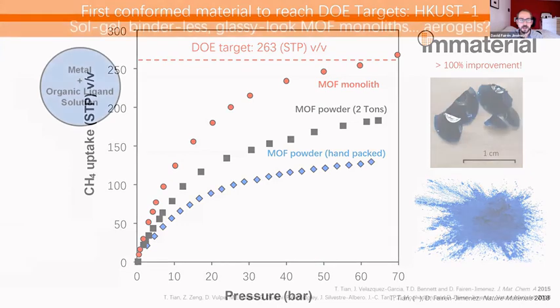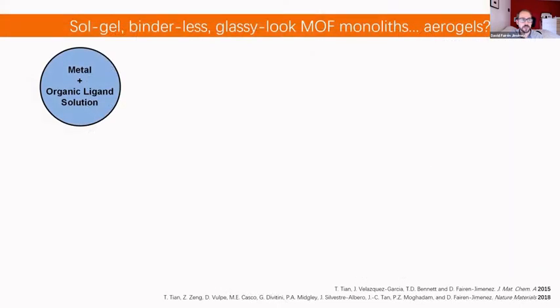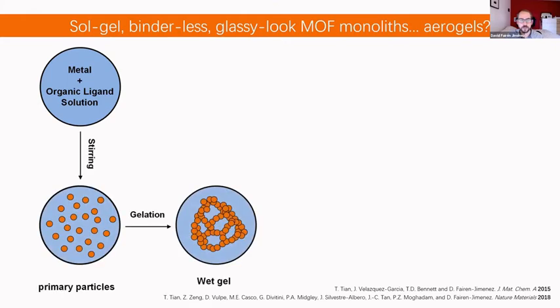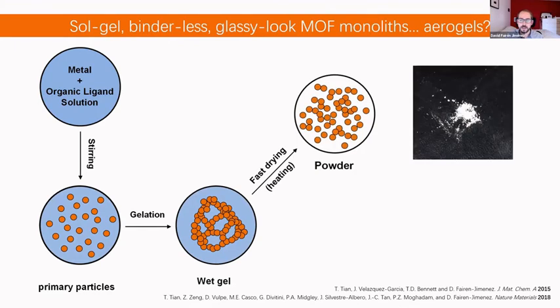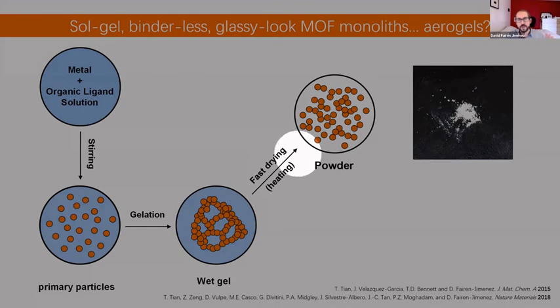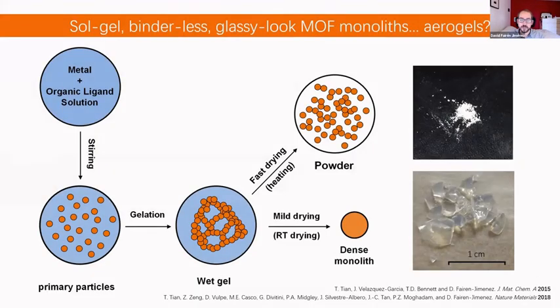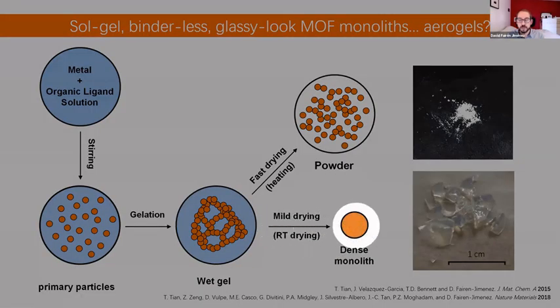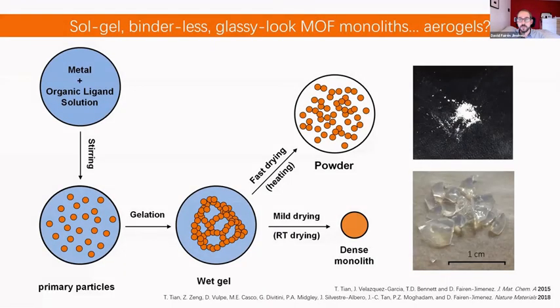And the idea behind this is that we have metals and organic ligands in solution. We have the synthesis of primary particles. We create what we call a wet gel. And if we have a fast drying process, okay, remember this student knocking at my door, he was putting the samples into the oven and he was getting a powder of the MOF. But when doing this slowly, for example, because you forget your sample in your vents, you are able to have a very mild drying process at room temperature. And in this case, he ended up with this very dense monolithic structure that you can see here on the right. Okay, big difference between this powder and this MOF. It's the same material, it's the same structure. Beautiful materials that we can really create.